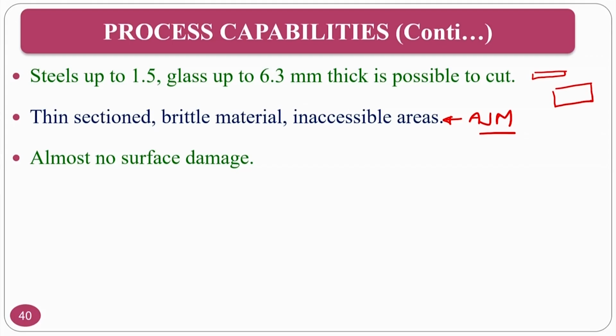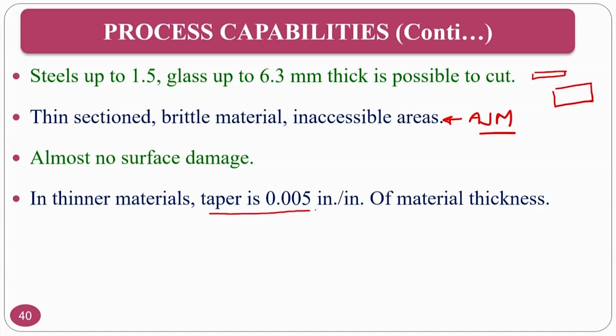Almost no surface damage, because there is a gap between abrasive particles. At the same time, heat generation in this process is normally low because you have air, which acts as a lubricant or coolant in this particular action of abrasive jet machining, and there is no surface or subsurface damage. In the thinner materials, taper is 0.005 inch per inch of the material thickness. That means if you are going for 1 inch, 0.005 inch is the taper normally observed. If the customer's requirement is very strict, then you have to think about some other processes. If this is within the limits of their requirement, then you can go for the abrasive jet machining process.